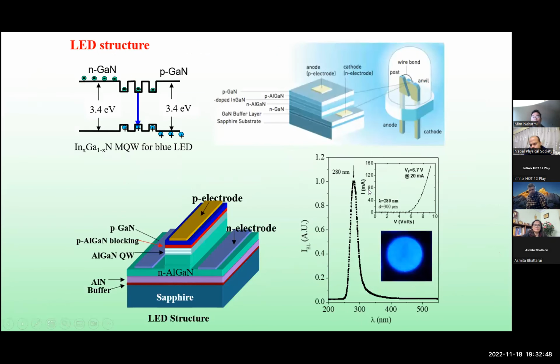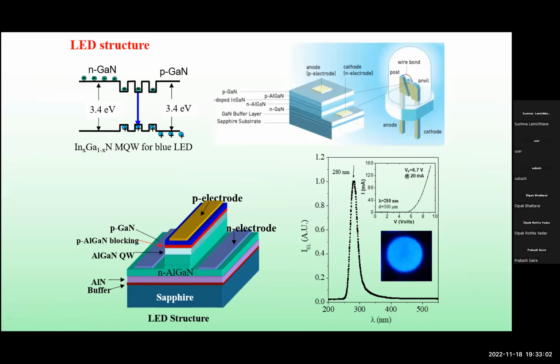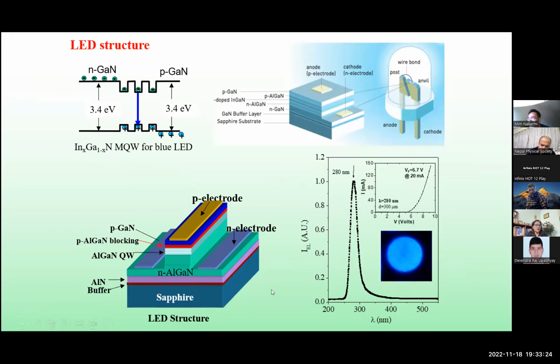All right, so this is a little bit of practical knowledge, with some pictures of real LEDs. Most of the time it's not only one well. Normally it has multiple quantum wells for higher efficiency, and these wide bandgap materials are grown mostly on sapphire, and it's not only one N-type and P-type, because there are lots of things to take care of when we grow the crystal. We like to have a high crystalline quality, and once we grow on a different substrate, we have to manage the stress, otherwise it will crack, and the crystal structure could be different. And there are also many layers required, thick layers required for the contacts.